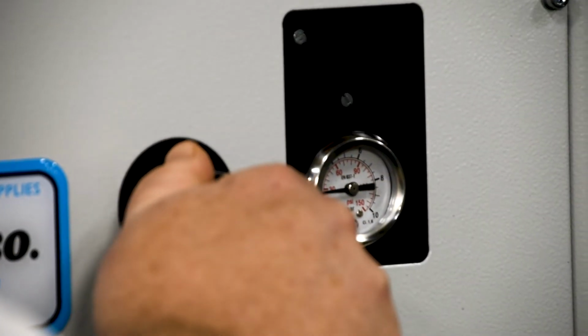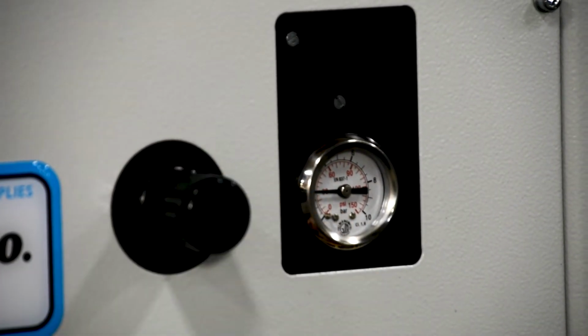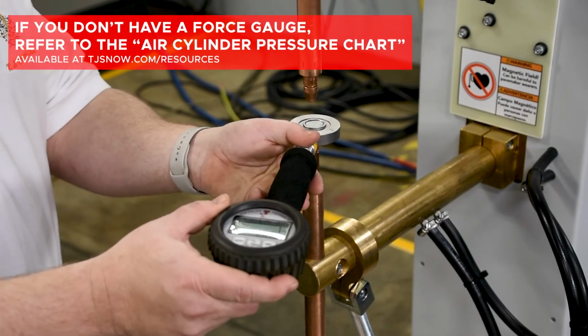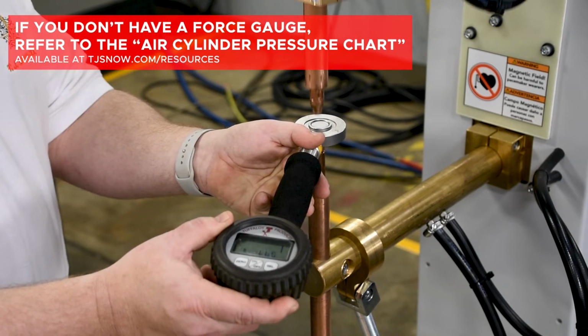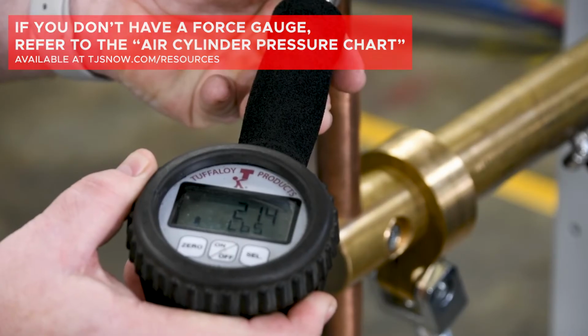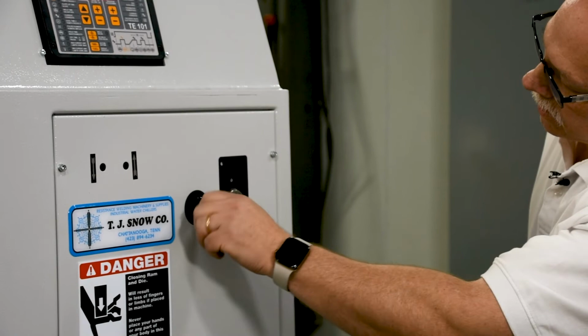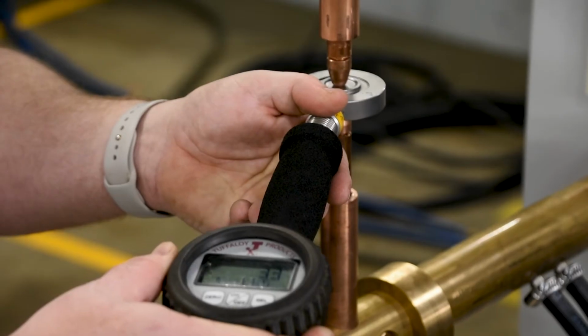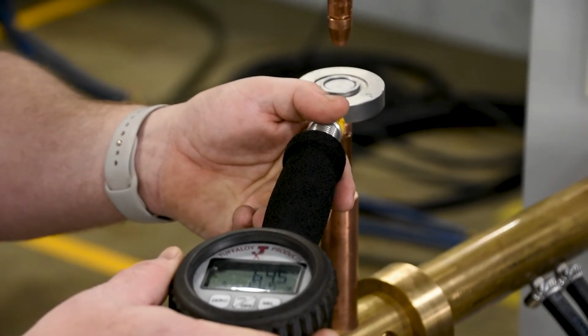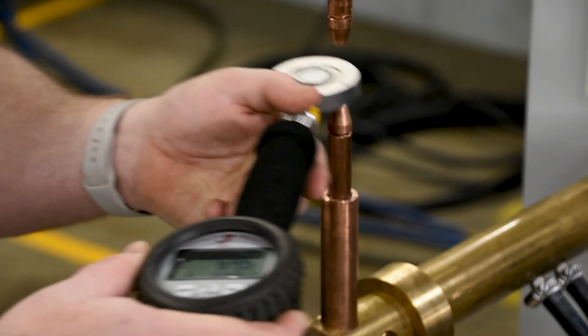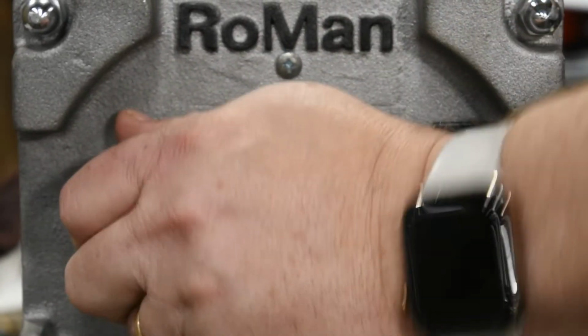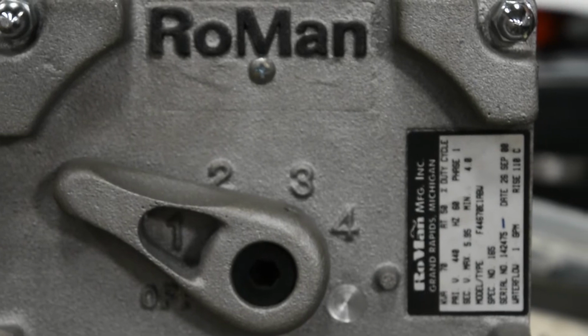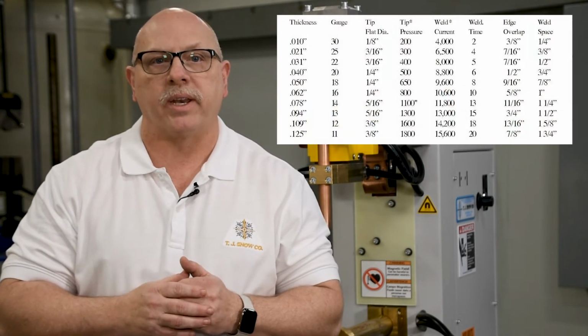We'll set the weld regulator to 30 PSI to start. With the proper electrodes installed and aligned, place the load cell between the electrodes and cycle the machine. Based on the reading on the force gauge, you'll need to increase or decrease the air regulator as necessary and recheck until the force gauge reads 650 pounds force. The next step is to set the welding transformer tap switch, if provided, to the lowest setting. With these steps done, we can now program the weld controller based on the chart recommendations.